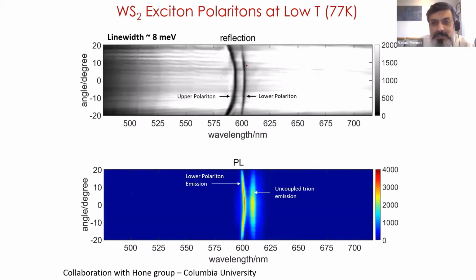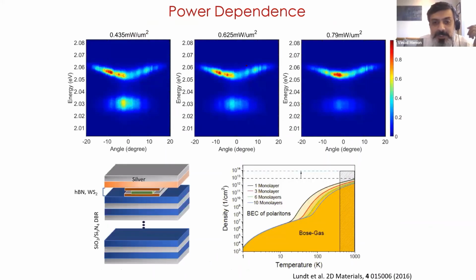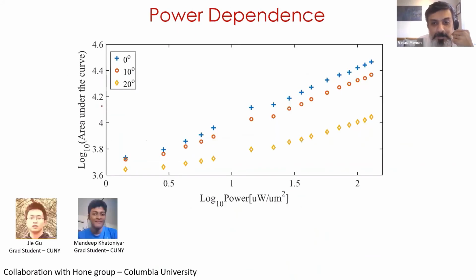We are trying to do condensation of polaritons at low temperatures. We've got some evidence of things condensing, getting to K equal to 0, but one of the big bottlenecks we are having is the fact that there are trions in the system, and we are trying to address these problems. But one promising aspect is that if I look at the intensity at K equal to 0, which is blue, it increases at a slope that is higher than the slope at K equal to 20. Which means that there is more polariton scattering to K equal to 0. So we are in the right direction of getting some condensation effects.